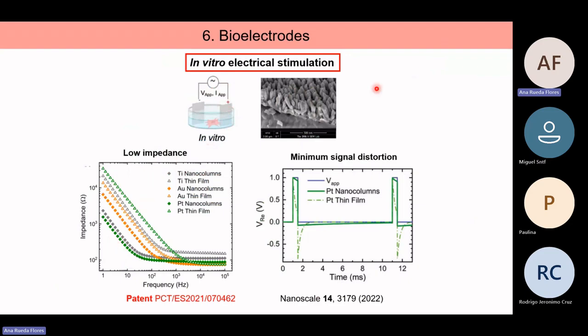What does it mean? We will transfer signals using an external electrical power source. But then the electrode will transfer the signal into the physiological media, and those signals can be different. As you can see here, in blue is the voltage that we apply to the electrode with the external power source, in this case square pulses. And in green, you have the response of the electrodes, what the electrodes deliver to the physiological media. In the case of the thin film, it's the dotted line, and you can see that the profile is quite different, especially in this region, compared to the blue line. So we are losing control of the electrical signal.